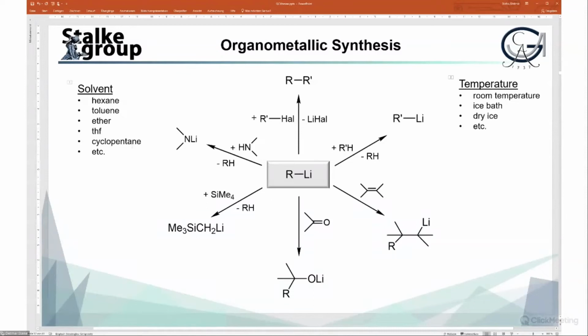Most of the reactions are done at chilled temperature. At least you need an ice bath, even better a hard ice or dry ice temperature at -79 degrees. Some reactions are done at room temperature, but not at elevated temperatures.